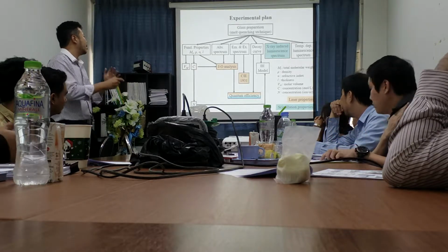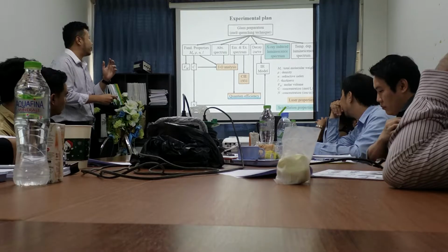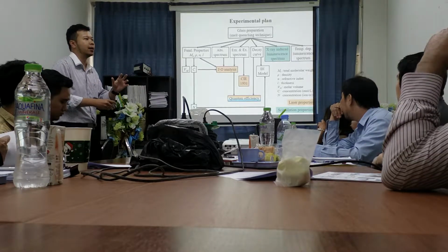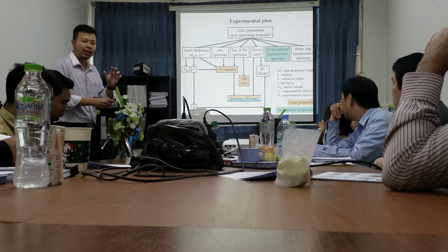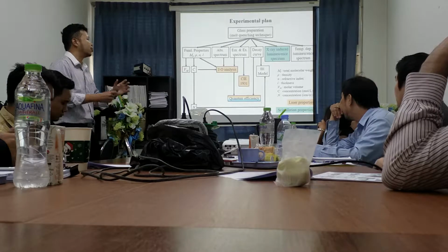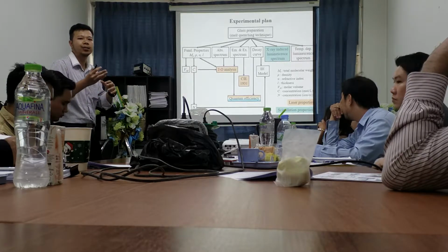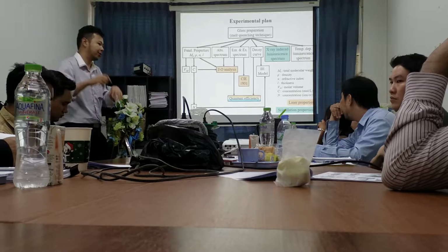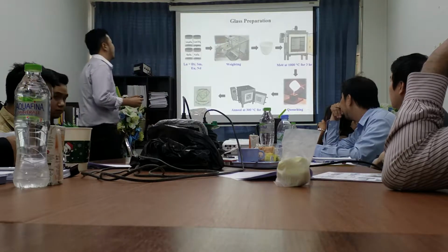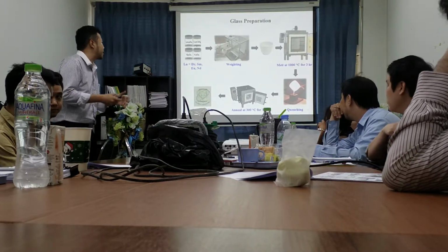And finally, I fit the decay curve that shows non-single exponential behavior, with the Inokuti-Hirayama (IH) model to explain the energy transfer process between the lanthanide ions. This is the glass production.